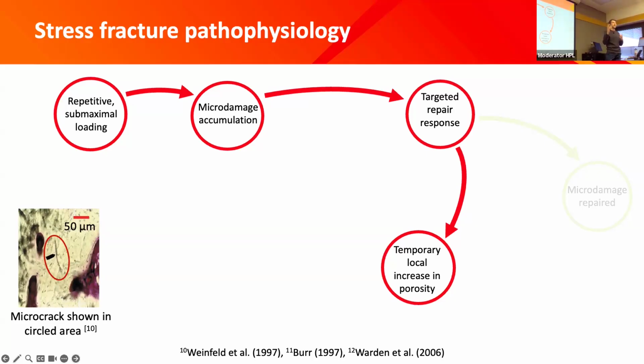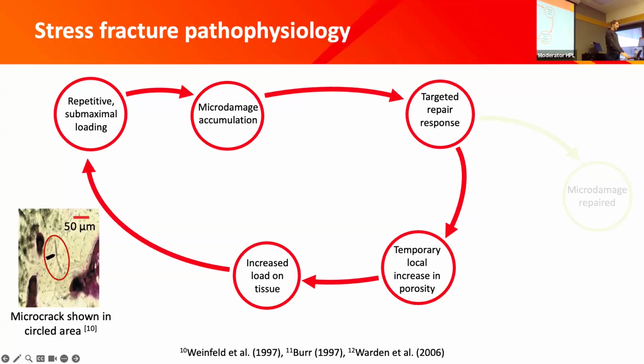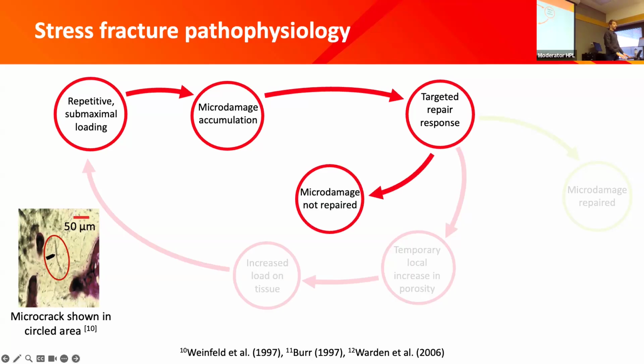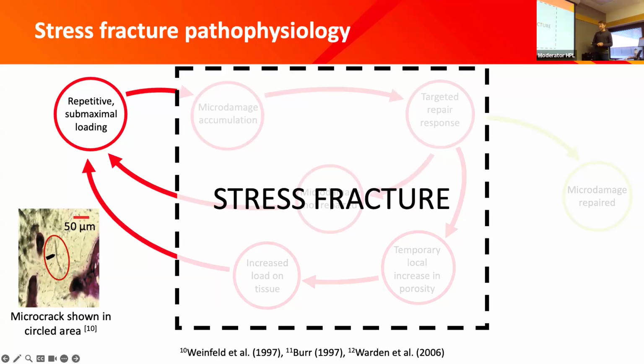So there's this period in between those two where there can be a temporary increase in porosity, and that could potentially lead to increased load on the remaining bone tissue that's left over. And if we continue this cycle, that could potentially lead us into a bad situation. The other way that stress fractures could potentially occur is if this targeted repair response just isn't enough. If our accumulation of microdamage is overwhelming that repair response, we have microdamage that isn't repaired, and if we continue this repetitive loading, that'll again lead us into this paradigm of stress fracture.